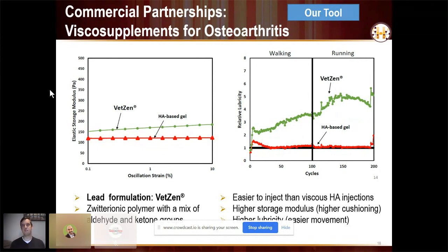The really exciting result, though, was the lubrication result. If you compare the hyaluronic acid-based gels, which again degrade very quickly, they're very shear thinning, with our cross-linkable zwitterionic polymer based on hydrazide and aldehyde/ketone groups, you see whether we're walking or we're running, we get between 3 to 5 times higher lubricity. So this is basically lower energy losses associated with the movement, which relate to patient comfort. It also means we can get away with a bit stiffer material and still not lose that patient comfort.